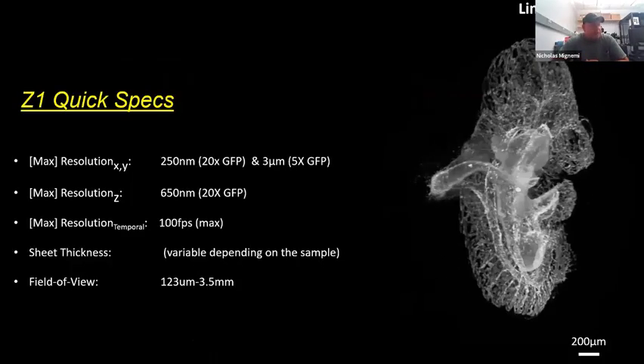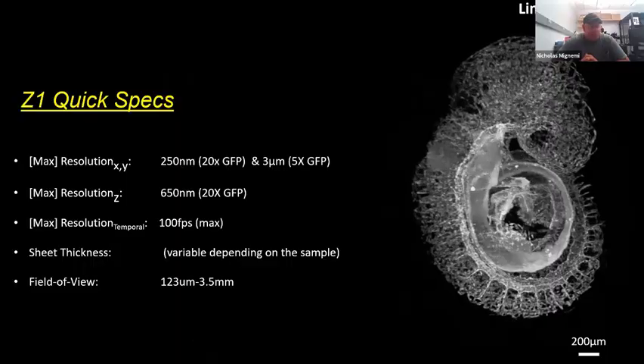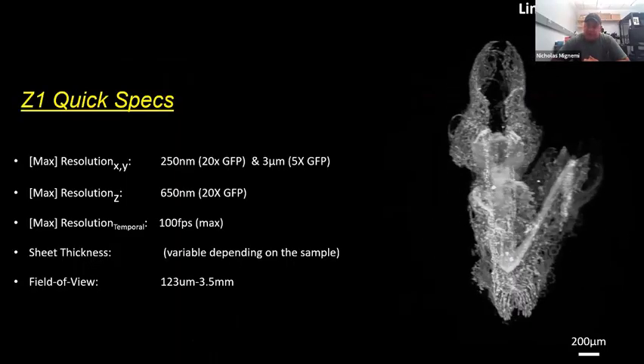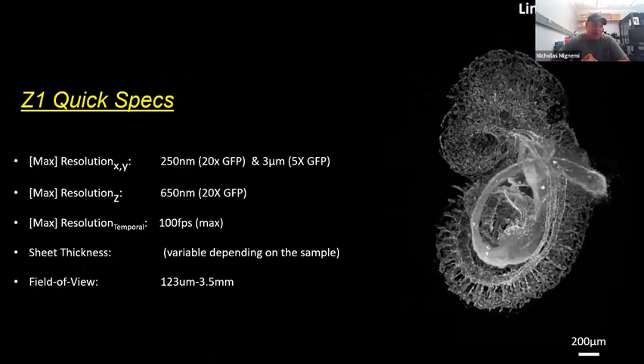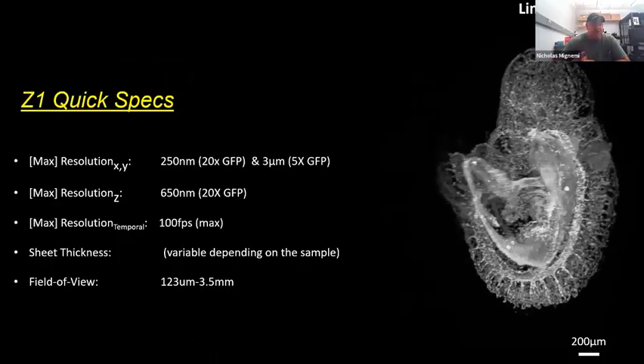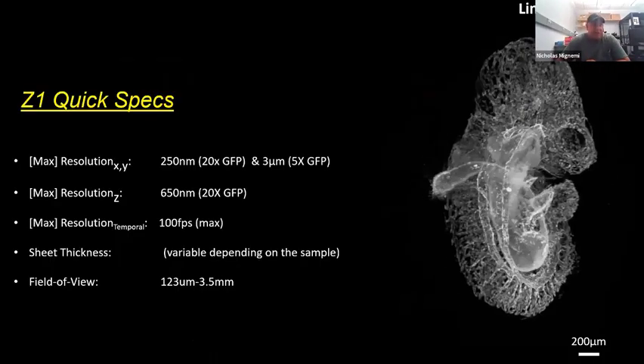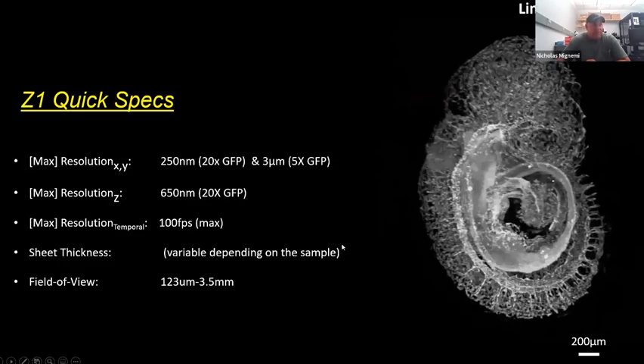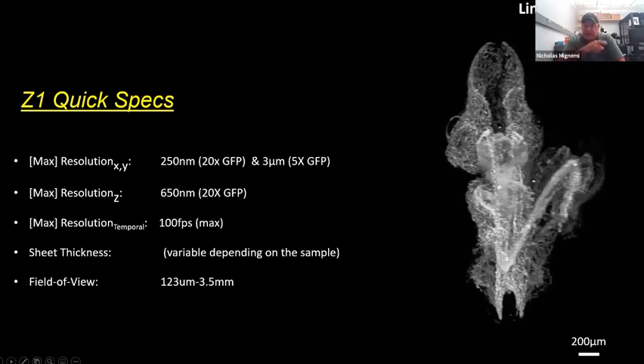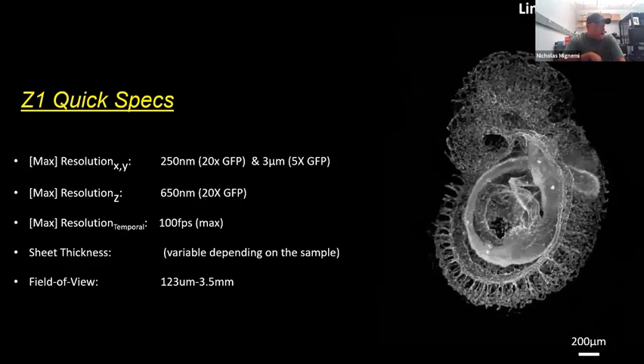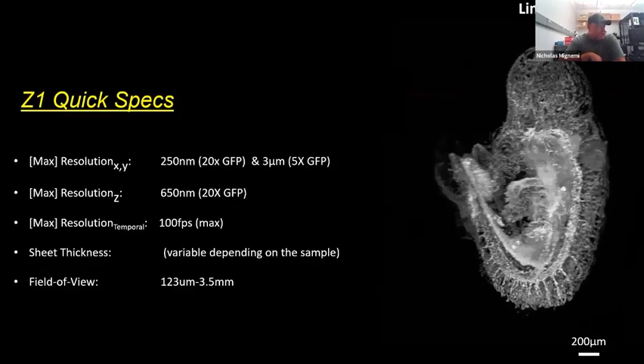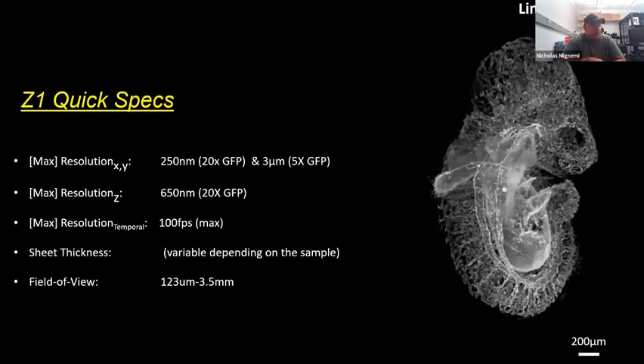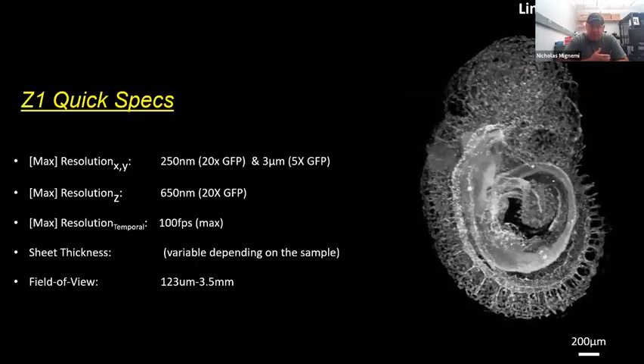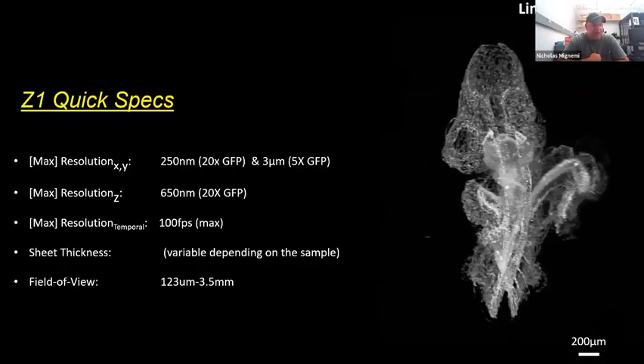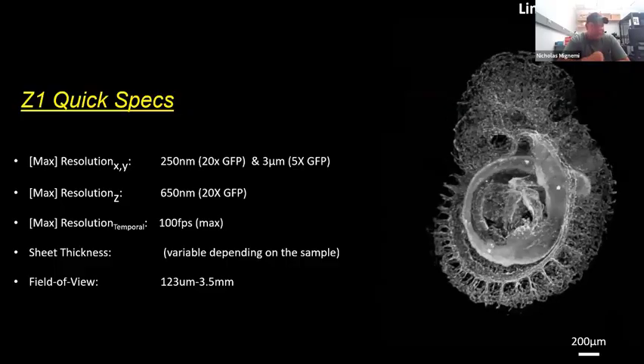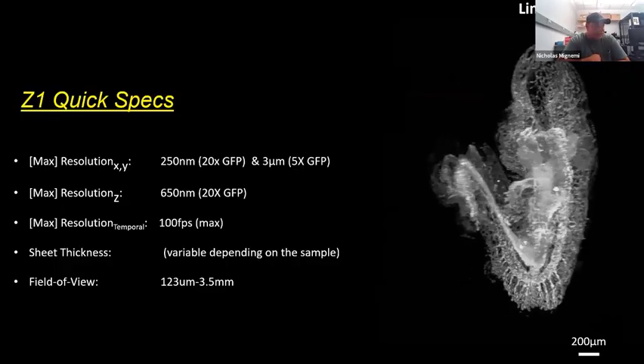So the max res we can do on the Z1 is about 250 nanometers with the 20X, or about 3 microns with the 5X. And just so you have a frame of reference, this is an E9 embryo captured by Lynn from the Magnuson lab. And this is a 5X imaging objective. The max resolution in Z for the 20 is about 650 nanometers. The system is fairly fast. It's not particularly faster than a spinning disk, but it is fairly fast. It's not terribly slow at all.